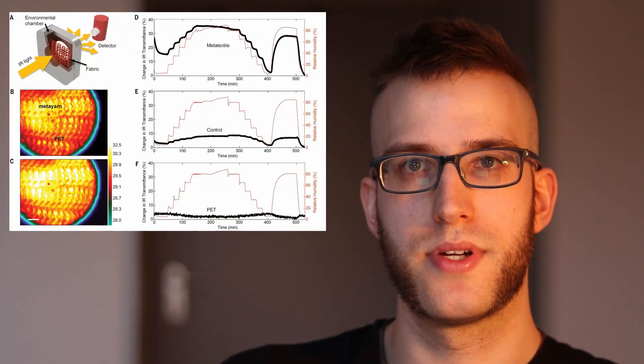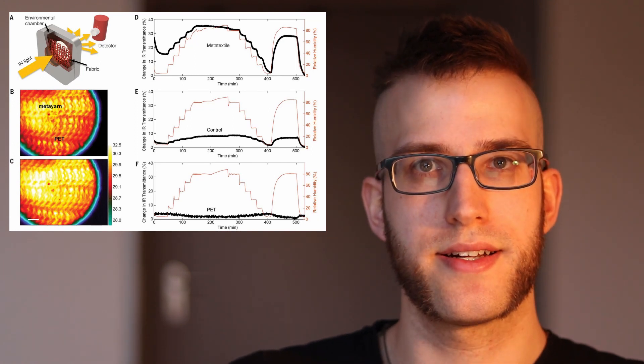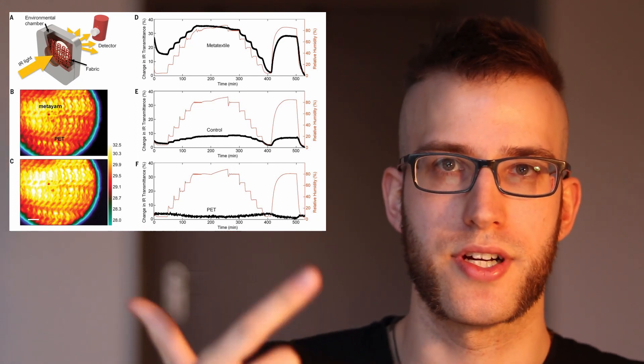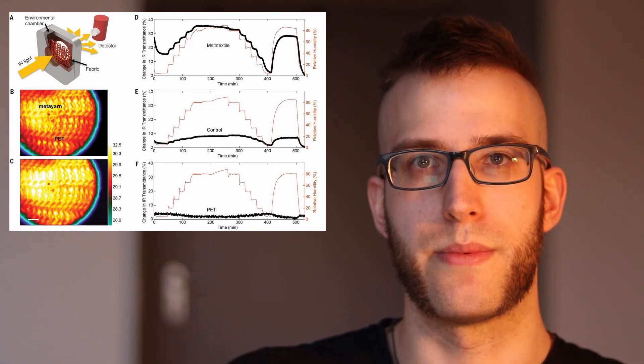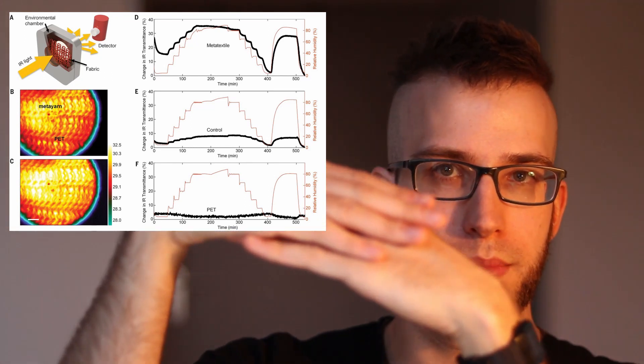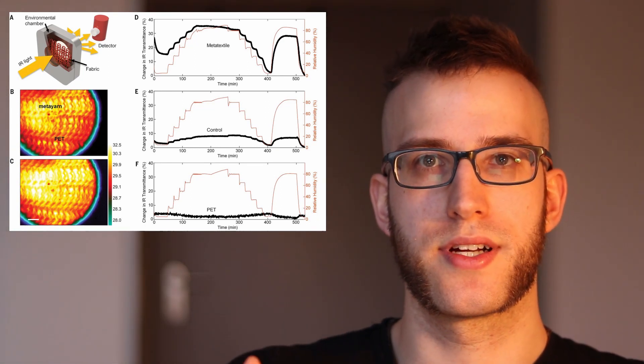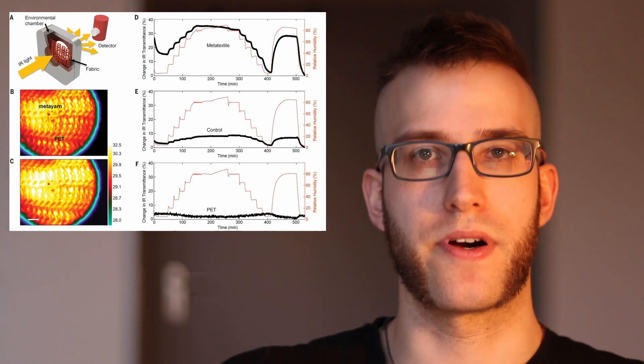The scientists tested this fabric by putting it into an environmental chamber with a controlled environment and shining infrared light through it onto a detector, while controlling the temperature and humidity in the system. Only the newly discovered metatextile reacted to the change in moisture or temperature, in comparison to the control fabric. The control fabric was the same bimorph fiber — so it reacted to the moisture — but it didn't have the carbon nanotube coating, so it didn't react to the infrared radiation.